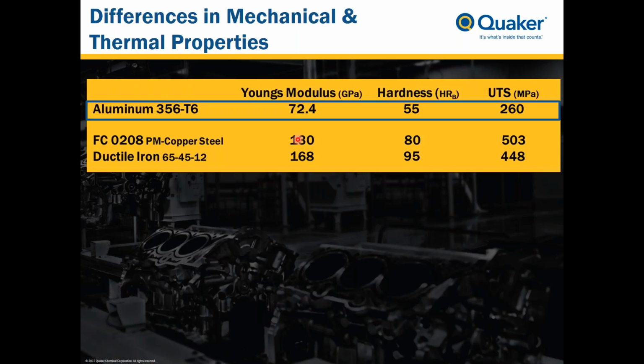If we look at the differences in the mechanical properties first, what's shown here in this table are three properties of the metals that are involved in this part and subsequently involved in the machining. First is shown the properties of aluminum 356 T6. And what is shown is the Young's modulus, the hardness, and the ultimate tensile strength of the material. And then, in contrast, are two ferrous materials that are used as the main bearing caps: the 0208 powdered metal, and a 65 grade ductile iron. They're both very commonly used in the fabrication of the main bearing caps for the crankshaft.